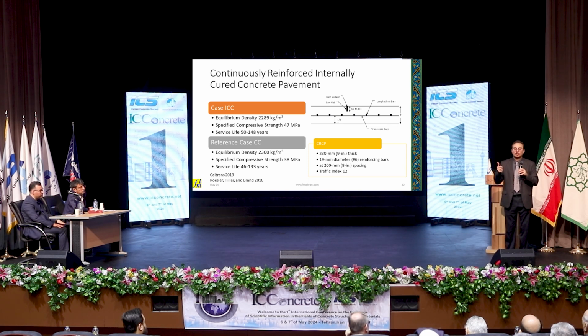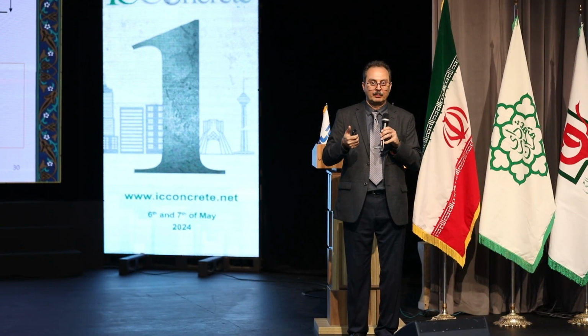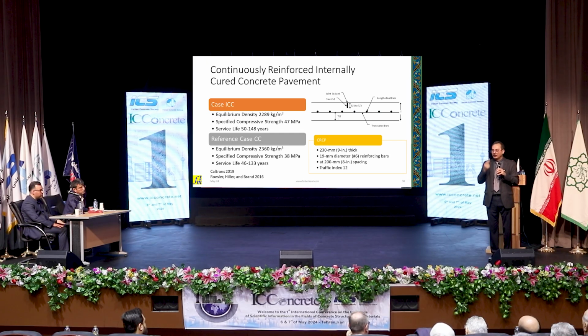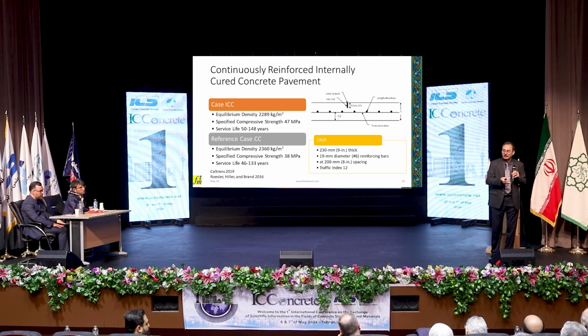Result, strength goes up again. Please never ever tell anyone that lightweight aggregate has less strength than normal weight. Please don't. The strength goes up. Service life goes up. How come? You have more hydration. You have no crack. This one works. There is zero cracking, and there would be no penetration of chloride ions into the concrete ever. Done.